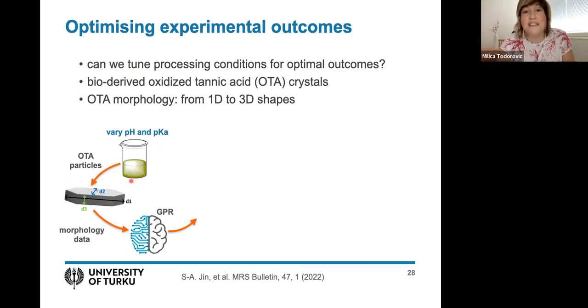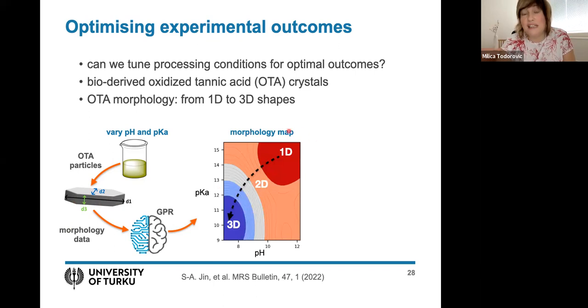So this was chemical synthesis of tannic acid, and they put it in solution where they could vary two parameters, pH and pKa of the solution. So those are our experimental variables. And they created several samples, which they characterized by taking SEM images. And they showed some particles, and then we measured their dimensions from the SEM images. And we took these dimensions and turned them into data points on particle morphology. And then we put this into Gaussian process regression to compute a surrogate model. Only this time, the surrogate model is for particle morphology in the phase space of these two variable experimental parameters.